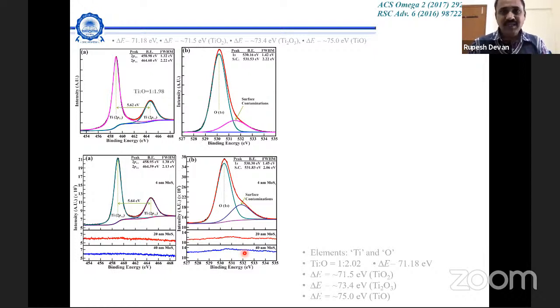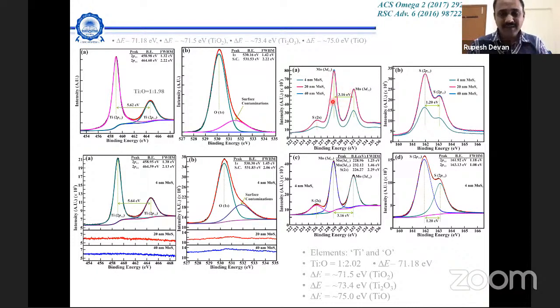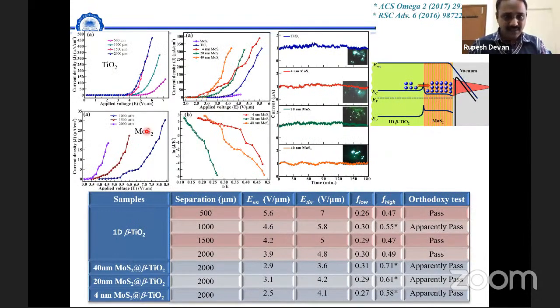At the same time, the MoS2 signal was lower for the 4 nanometer layer because the amount of MoS2 was small. When you move to 20 nanometer, the signal increases. So this indicates that what we are saying is true, that we have 4 nanometer, 20 nanometer, and 40 nanometer layers of MoS2. When we checked the field emission properties, on pure TiO2 we could get a turn-on field only up to 3.9, but when we coat the MoS2 layer, it is reduced to 2.5. That means nano heteroarchitecture formation really helps to improve the properties.